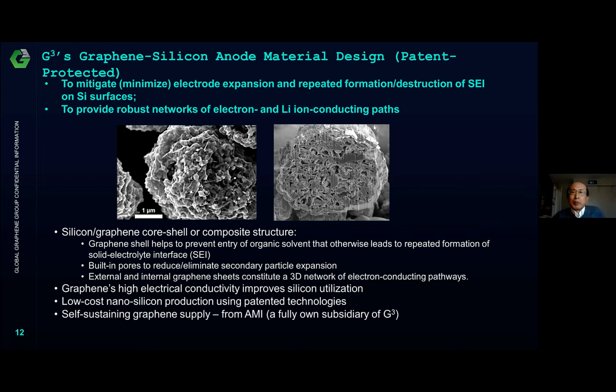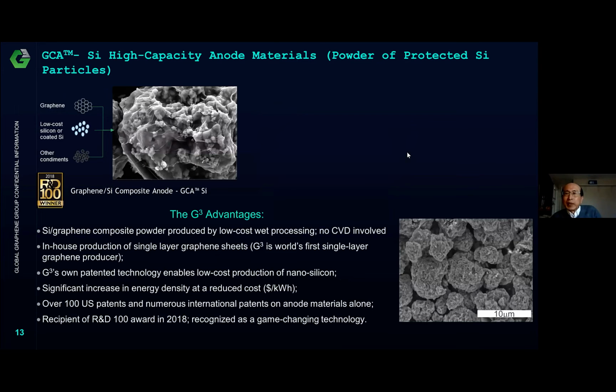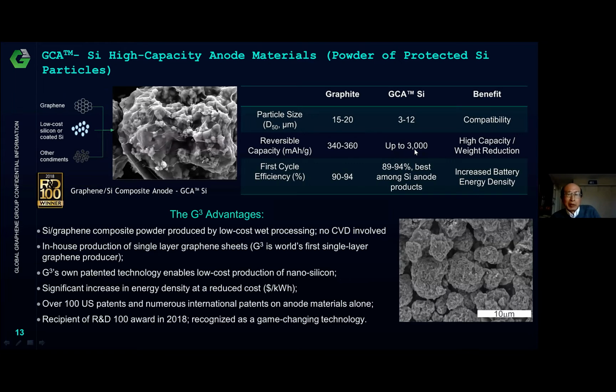Now, this is our product here. We have an anode material that has a specific capacity of up to about 3,000 milliamp-hours per gram, as opposed to 350, 360 milliamp-hours per gram for graphite. We have a very good product here, and we actually received an award, the so-called R&D 100 award, in 2018.